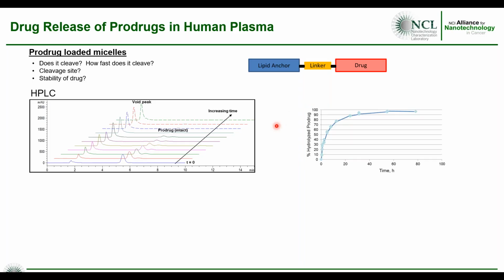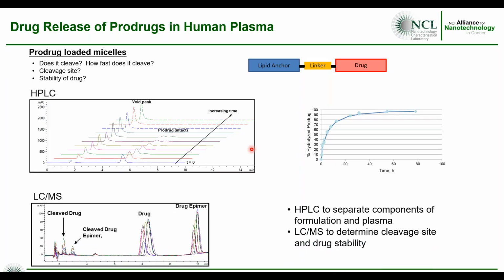The reason we did this, and I kind of mentioned this on the previous slide, is that especially with the longer time points, if you have any ester linkages in your drug, the esterases in plasma will start to degrade or break those bonds as well. And essentially you have a nice mess to try to analyze because that cleaved drug is no longer intact. It actually itself has cleaved itself. So this is a different approach of looking at hydrolysis rates of prodrugs. We also did HPLC to separate out the components of the formulation from plasma, and we can use LCMS to determine the cleavage site as well as any drug epimers and cleaved drug products.